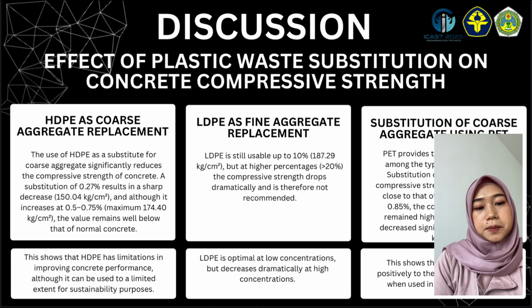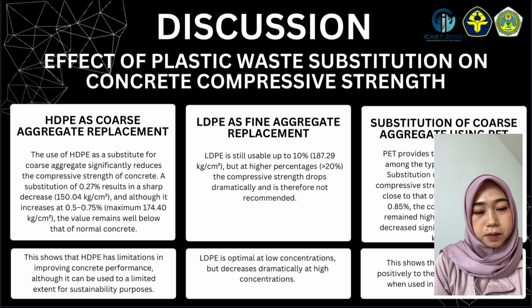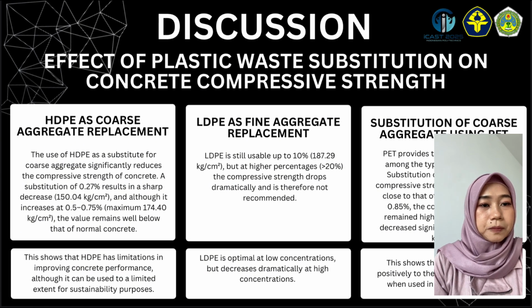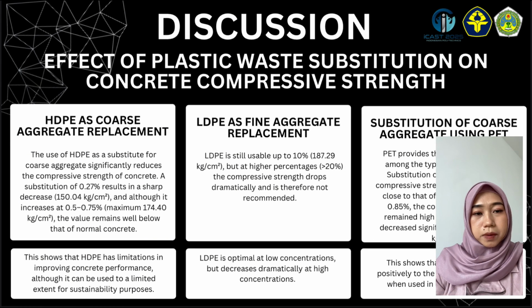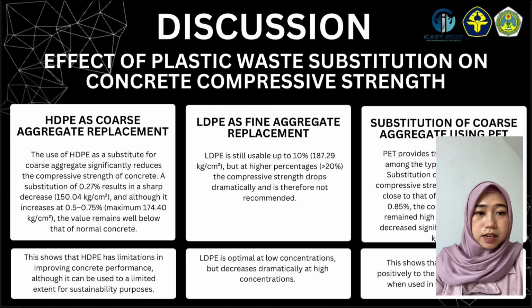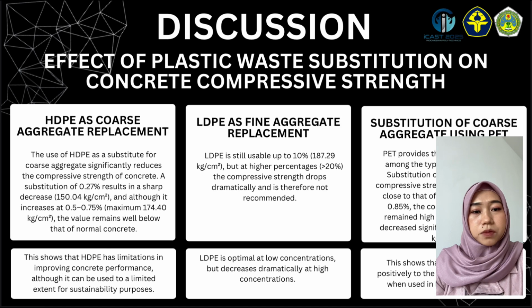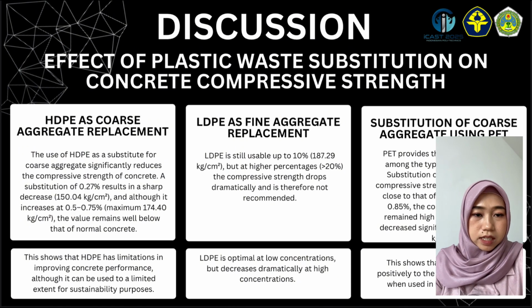This shows that HDPE has limitation in improving concrete performance, although it can be used to a limited extent for sustainability purposes. LDPE is still usable up to 10%, but at higher percentages, the compressive strength drops dramatically and is therefore not recommended. LDPE is optimal at low concentration but decreases dramatically at high concentration.